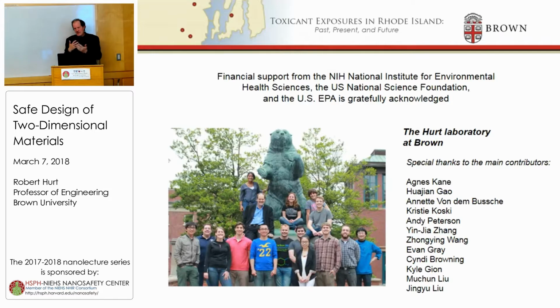And we have a set of them. Some of them are as thin as the ones you're working with, 3 or 4 layers, and some of them are up to 20 layers. And so they're not really atomically thin, but they do have these sharp edges, and their edge structures have points that are quite thin. And the simulations, some of them are on monolayer graphene, but some of them also used multi-layer graphene in the simulation. And the energy barrier goes up as the edge gets thicker, there's no doubt.